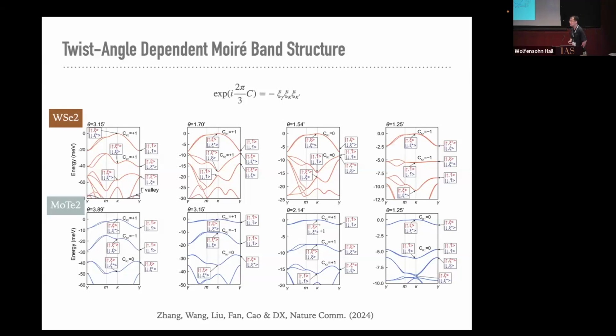Okay. So in fact, when we first wrote the paper, we actually assigned this 1, 1, -2, because remember that the Chern number is only defined modulo 3. So 1 and -2 for us is the same, right? And when you see two Chern number 1, just, okay, let's make it the -2 so we can close this manifold. But later we actually performed more detailed calculation based on Wannier functions and confirmed this is actually 1. Now this is already super interesting because I think before this calculation, even for us, we didn't expect to see these multiple Chern bands, always Chern number 1.